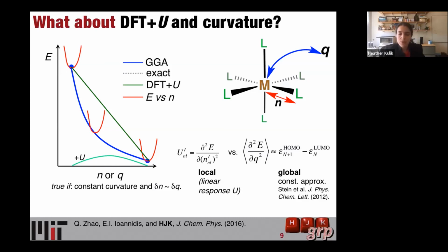But that being said, for a given electronic state, Hubbard U values, anecdotally about 6 eV or below, will linearly alter your properties. So you will know, if my PBE band gap is here, increasing the U by this much, say scanning through in 1 eV increments, will tell you how much you can expect your band gap to shift.